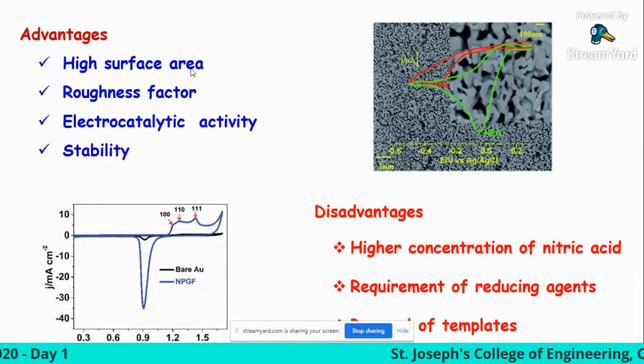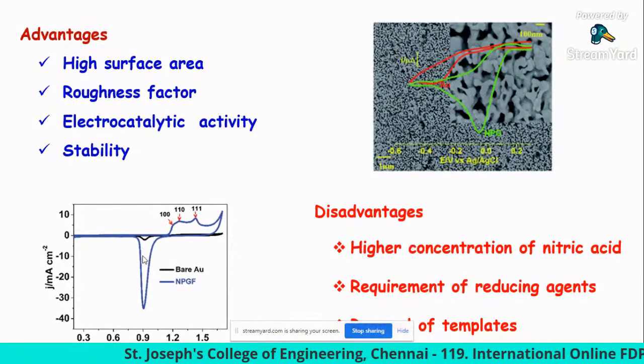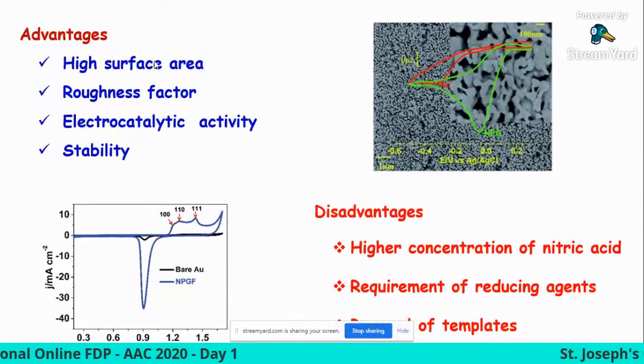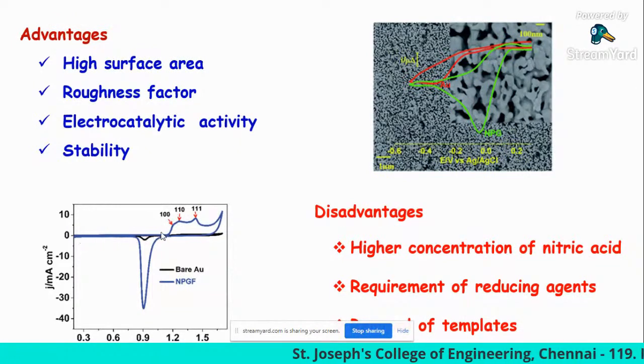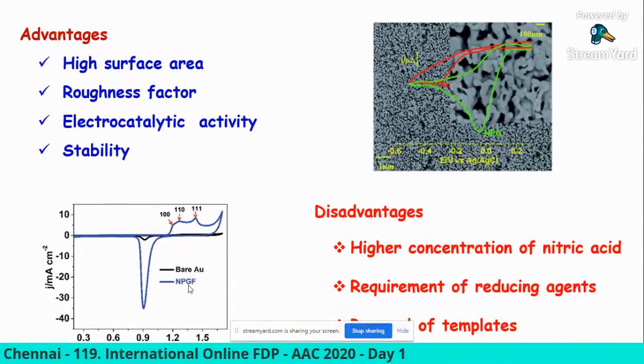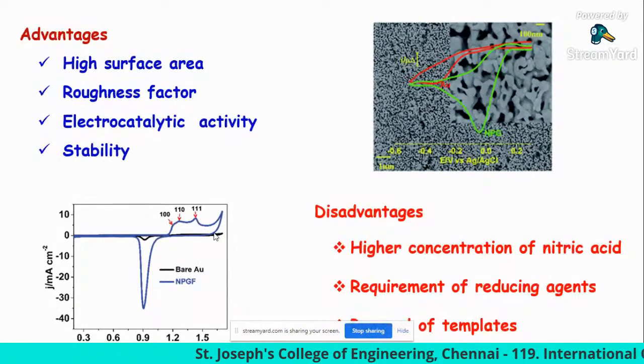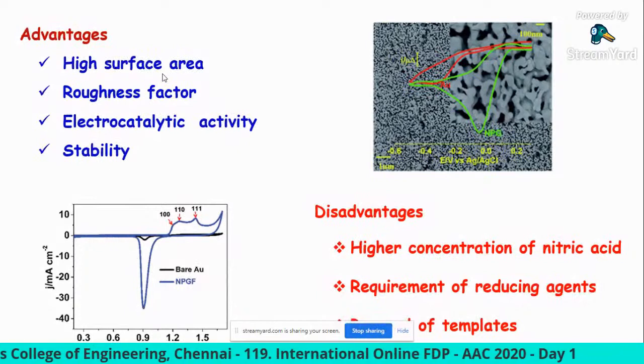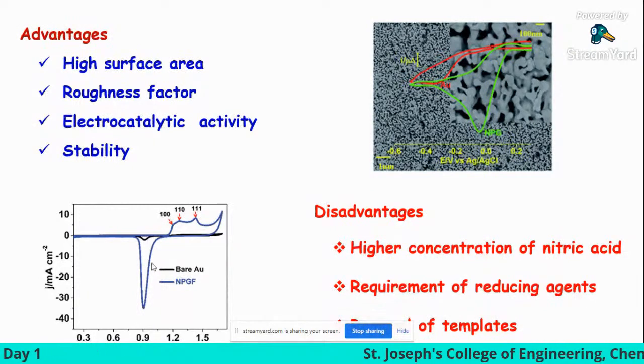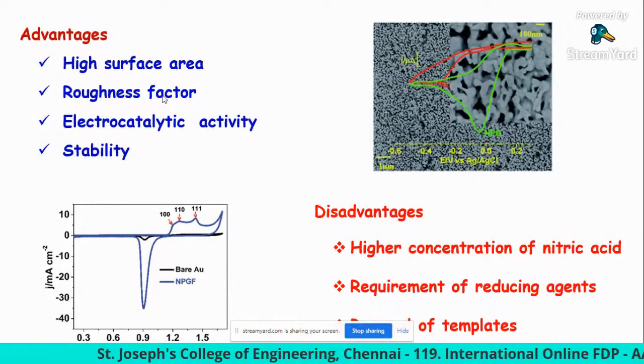So as I told you earlier, this type of material has very high electrochemical surface area and roughness factor. So here is an example to understand how this type of material shows the high surface area and roughness factor. This is the cyclic voltammetric response of bare gold, that means a flat gold electrode, and this is the nanoporous gold electrode. Here you can see a clear oxide, these three are the Au oxide peaks, and this is the corresponding Au oxide reduction peak. So the high surface area and roughness factor is calculated based on the reduction peak. If you calculate the area of the electrode, there are some equations, so you can calculate how much the electroactive area is.